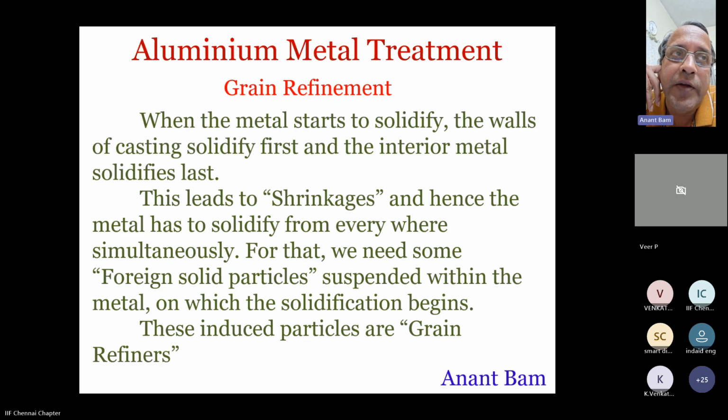So its severity will reduce to 1 by 10,000. It will be negligible. Although the volume of that shrinkage will be equivalent to the volume of initial shrinkage, but just because it gets distributed all over evenly and its individual appearance is minuscule, it becomes redundant.